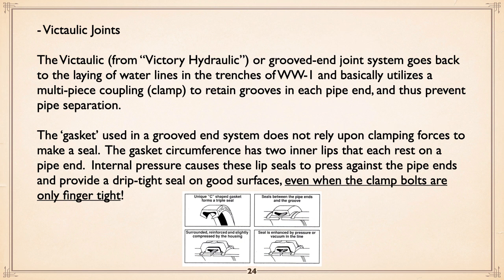And basically what it does, it uses a multi-piece clamp to retain grooves in each pipe end and thus prevent separation. The gasket used does not rely on clamping forces to make a seal. It has two inner lips. You can see on the upper left sketch there, a unique C-shaped gasket. So it has two lips that fit on the ends of the pipe. So you put that on, with the pipe in. Then you've got the coupling itself, which retains the grooves. Because it's a lip seal, internal pressure causes the thing to seal even better. And you end up, if the surfaces are half decent on the end of the pipe, with an absolutely drip-tight seal.